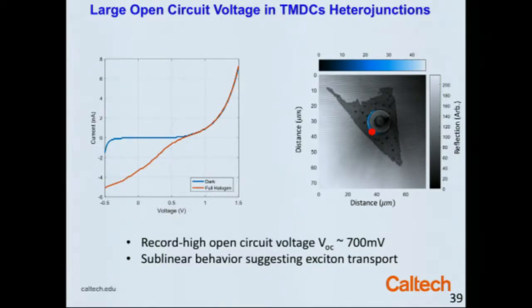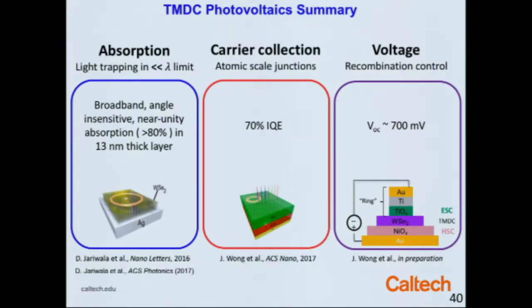But they're relatively good, and that enabled us to get to a record voltage of about 700 millivolts. That's not quite where it needs to be, but it indicates the direction for progress, at least. So at this point, we've been able to make highly absorbing films with relatively respectable internal quantum efficiency, with some work to go on the voltage.